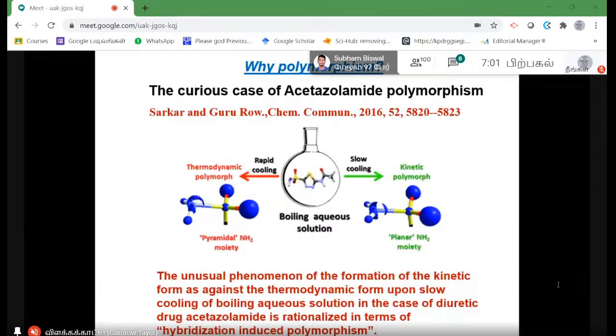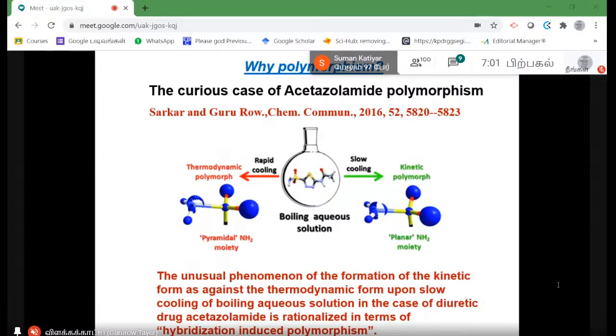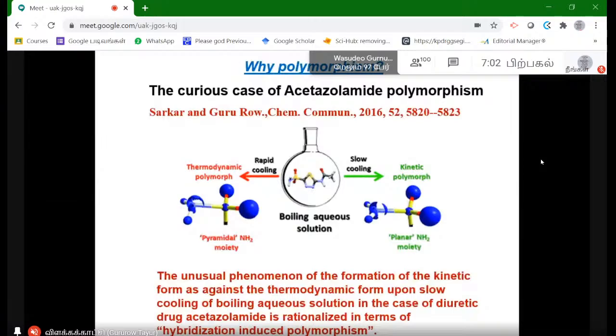The acetazolamide, when crystallized from a boiling aqueous solution, if we rapidly cool, it goes to what we call the thermodynamically stable polymorph. It forms a pyramidal NH2 moiety at the end of this. This is the NH2 moiety. The NH2 is a pyramidal configuration. It goes to the planar configuration when we cool it slowly. And it so happens that this is the kinetic polymorph. That means we can convert this to this one through a methodology.